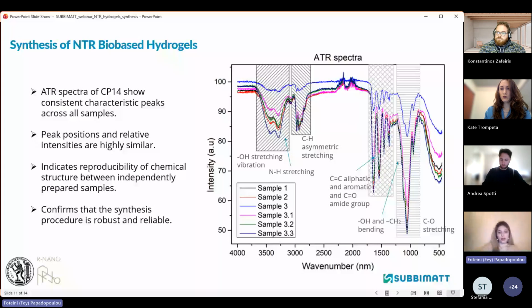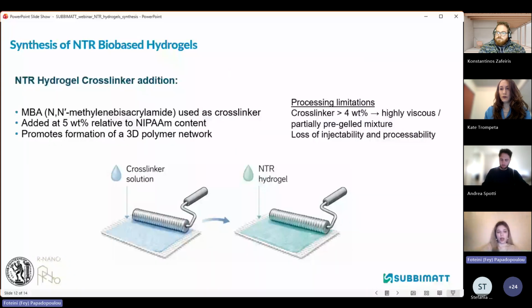And now comes a bit of a difficult issue. How can we graft and secure this hydrogel that we made onto the fabrics? The first route we chose was just to disperse it with a cross-linker and see how the fabric reacts. That was not enough. So we tweaked our synthesis route, our coating route, and we immersed our fabrics in the cross-linker, which is MBA.